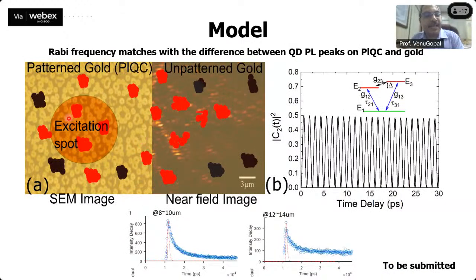The idea here is that we have quantum dot clusters which are on top of this plasmonic structure. The right part is the unpatterned metal region, and this part is the patterned metal region. The quantum dot clusters are excited with an excitation spot, and the emission from these quantum dots excites plasmons which propagate and excite these clusters on the unpatterned metal region. These two are slightly shifted in resonance due to Lamb shift, and there is resonant coupling between them at high densities. So you see these oscillations in the time domain, the Rabi oscillations, much longer than the plasmon lifetime, because these are exciting the plasmons.